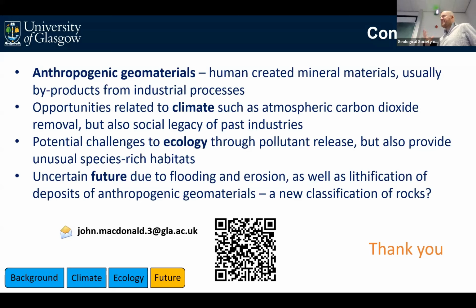Another possibility is that there might need to be some kind of dynamism in the system, some kind of energy, perhaps. Because we observe this at pretty much all of the coastal and indeed inland slag deposits we've been to in the UK, which are in contact with water, apart from one at Barrow-in-Furness. And the difference there is that it is behind a mudflat and a barrier island. So it's quite a hydrodynamically calm situation. So that's our hypothesis so far.